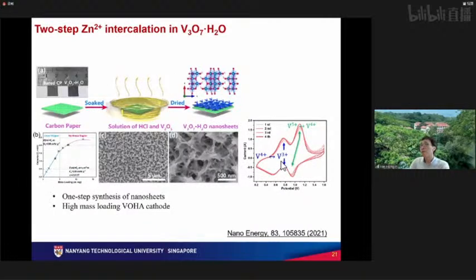And recently, in a collaboration with a group from Jinan University, they made this high mass loading vanadium oxide V3O7 with crystal water nanosheets. So this is also a very high mass loading array structure using a one-step hydrothermal method. They grow materials with different mass loadings and then identify the mass loading of about 5 point something. Okay. And the more important contribution of the work is that they use various calculation tools to verify the 2-step reaction processes, 5 to 4 and 4 to 3, the redox reaction for vanadium oxide.